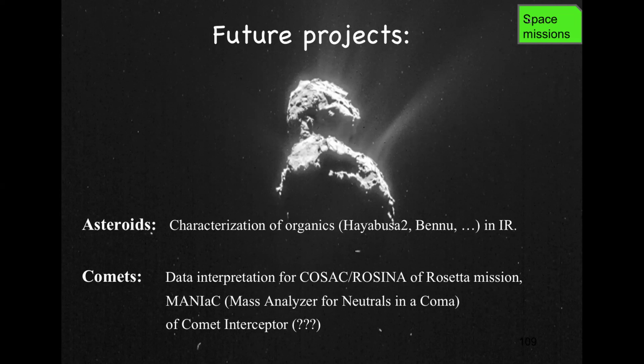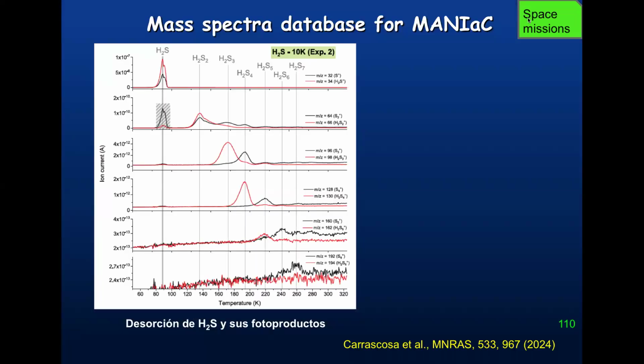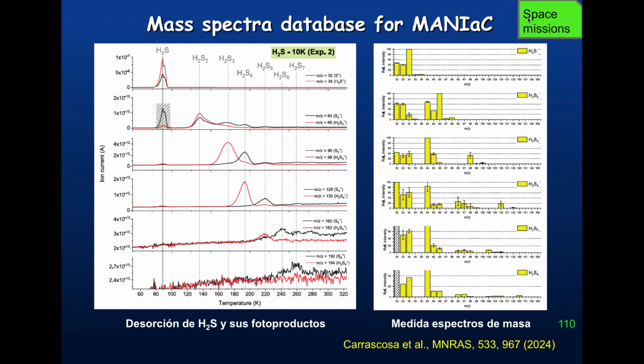on the MANIAC instrument of Comet Interceptor. In particular, we can provide the desorption temperature of the molecules in the comet, and also the mass spectra that we are obtaining in the lab, so that with the MANIAC data, in principle, we can provide this database of mass spectra to characterize what is being measured by MANIAC. So we can do it for sulfur molecules or for other molecules, so to say. So we have to synthesize these molecules in our ice irradiation experiments, and then obtain the mass spectra for comparison with MANIAC.